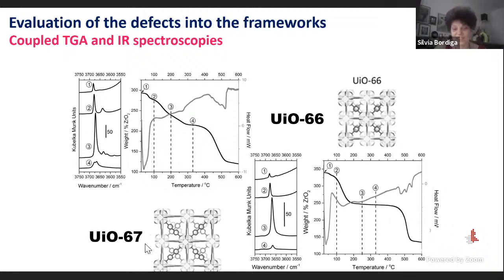In the case of, for instance, this material, we were able to obtain a TGA with a nice plateau, as reported here, but this is not always the case. For instance, for this material, instead, we obtain a much more complex TGA profile, and also the evolution of the infrared spectra shows us that in this case, we don't have just one family of OH groups as expected at the node of the zirconium cluster, but we have more than one site. And so for sure, in this case, we have a material with some distribution of defects, most probably lack of the linker inside the lattice.